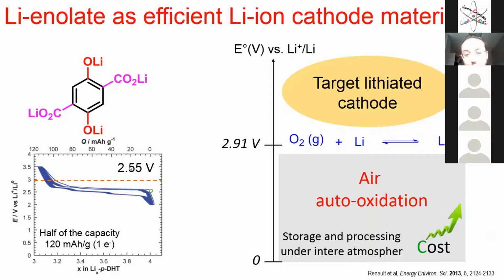So here we have 2.91 volt, which is the oxidation potential of oxygen versus lithium, because you have a lithium-containing molecule, and this lithium will react with oxygen, and this happens at 2.91. If you want to avoid this, your lithium-containing organic cathode molecule should have a higher potential than this value. Everything below this value will be subject to air oxidation, and this will cause problems for storage and processing, because you need a glove box to do this, and this will increase the cost of fabrication. So what we are looking for is lithiated organic cathode materials that can react at high potential, mostly above 3 volt.